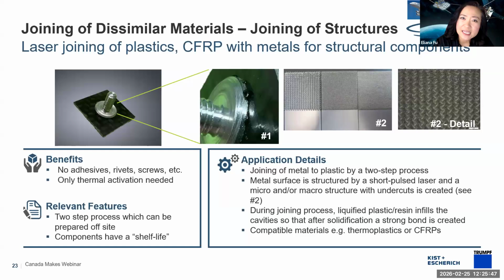Another thing you can do with laser joining is joining dissimilar materials. So this is an example of a carbon fiber reinforced polymer with metallics for structural components. So how do you do this without needing an adhesive or rivet or mechanical fastening? Only thermal activation. So a kind of two-step process. First, you would structure the metallic to be joined by roughening the structure so that it's more easy to accept the polymer inside. And then you melt the polymer so that it's not completely molten, but merely plasticized, enough heat to make it flow.